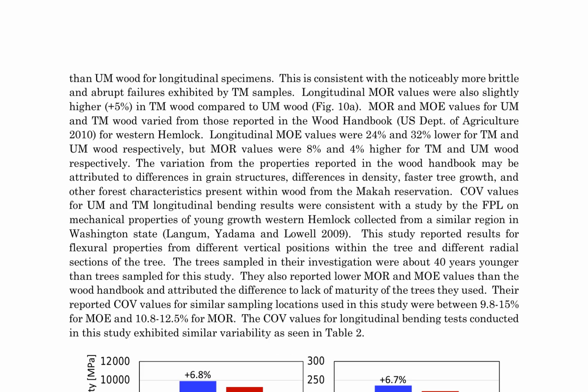Mechanical properties of thermally modified (TM) and unmodified wood specimens from the Makah Reservation were evaluated through longitudinal and transverse bending tests. Results showed that TM wood exhibited approximately 5% higher modulus of rupture, MOR, values compared to unmodified wood in the longitudinal direction, consistent with the more brittle and abrupt failures observed in TM samples.